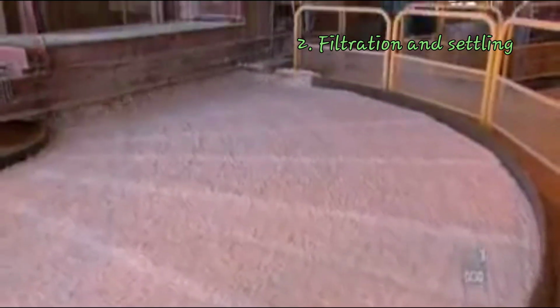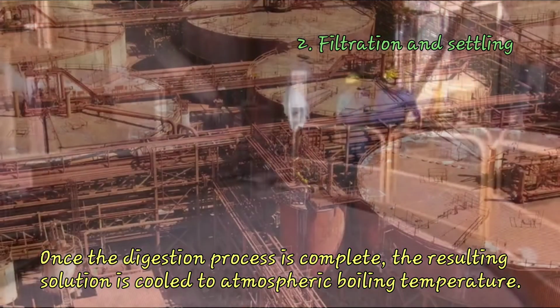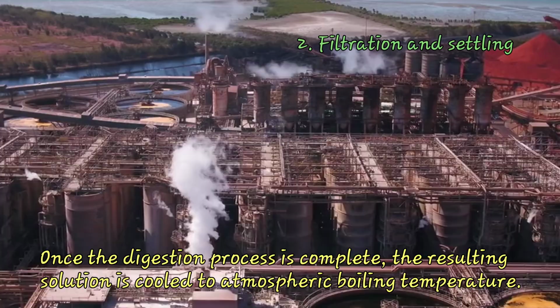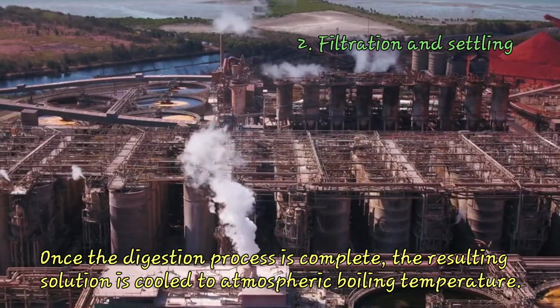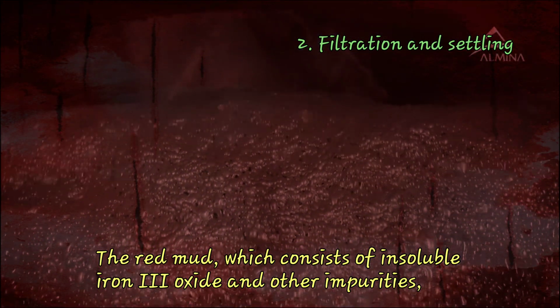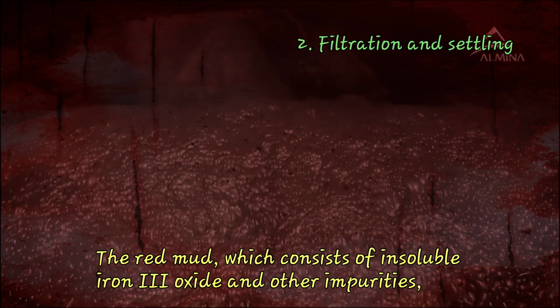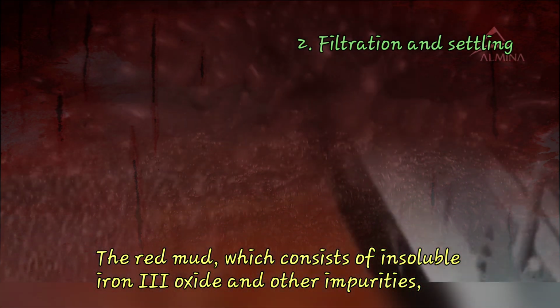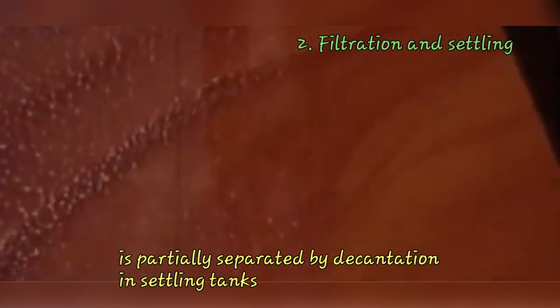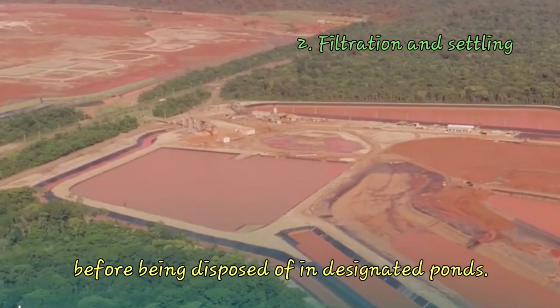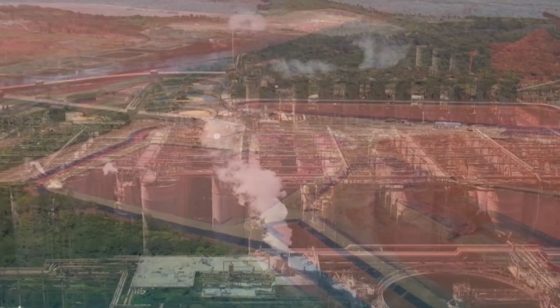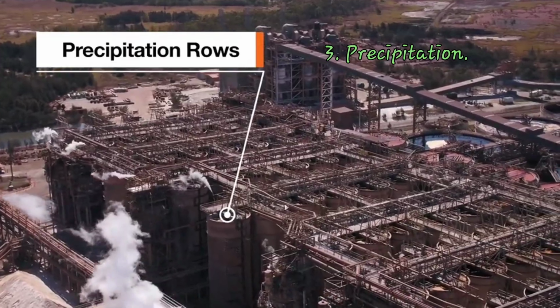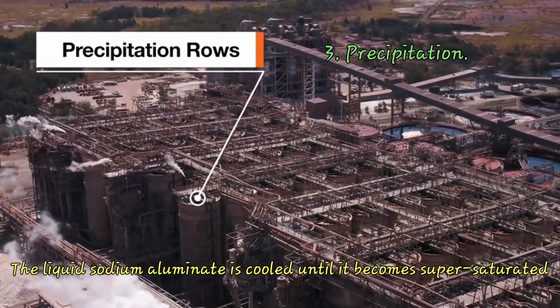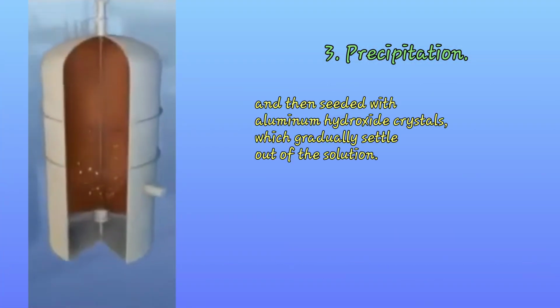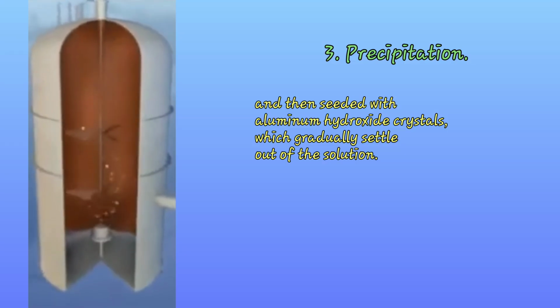2. Filtration and settling. Once the digestion process is complete, the resulting solution is cooled to atmospheric boiling temperature. The red mud, which consists of insoluble iron(III) oxide and other impurities, is partially separated by decantation in settling tanks before being disposed of in designated ponds. 3. Precipitation. The liquid sodium aluminate is cooled until it becomes supersaturated and then seeded with aluminium hydroxide crystals which gradually settle out of the solution.